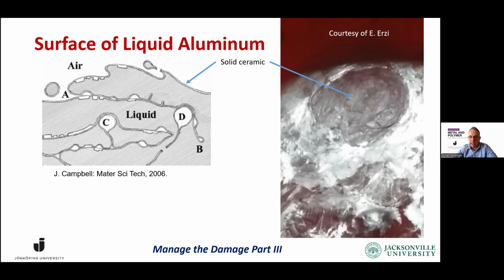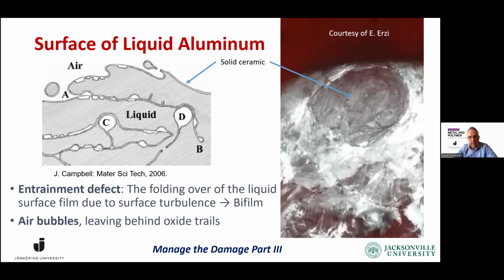So the more we interrupt the surface, the more damage is given to the liquid metal. The entrainment defect that we see is a folded over surface film due to the interruption or disruption of the surface. We also see air bubbles leaving oxide trails. We treat liquid aluminum as if it were water, as we're going to see in a few slides. So that is the root cause of the damage that comes back to haunt us eventually in our aluminum castings' performance.